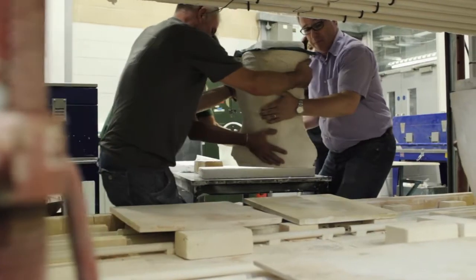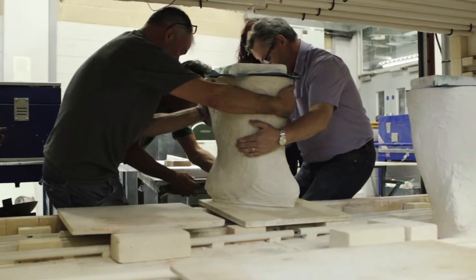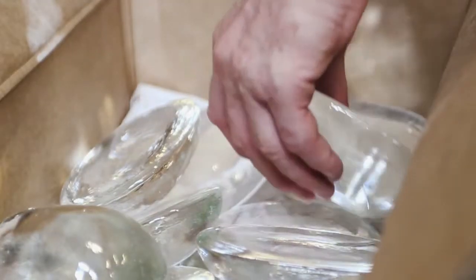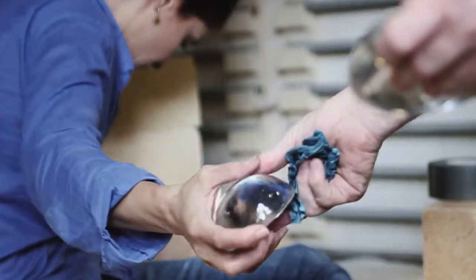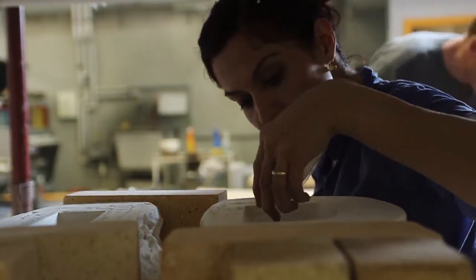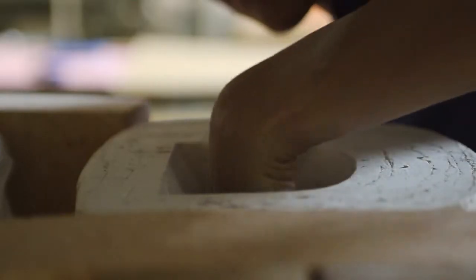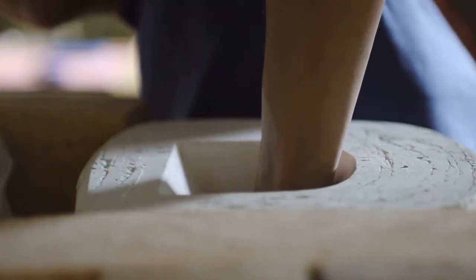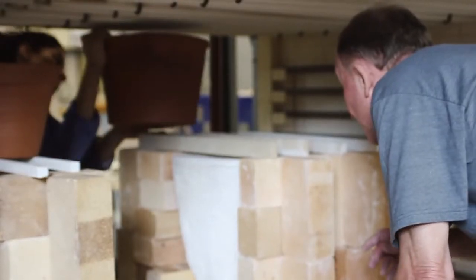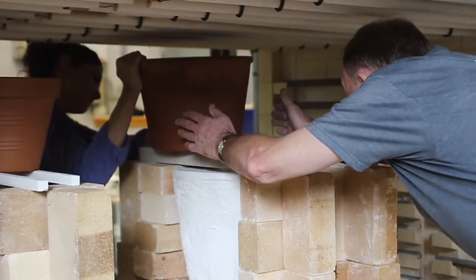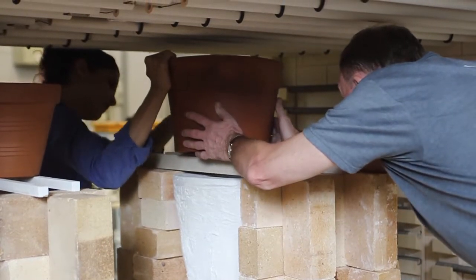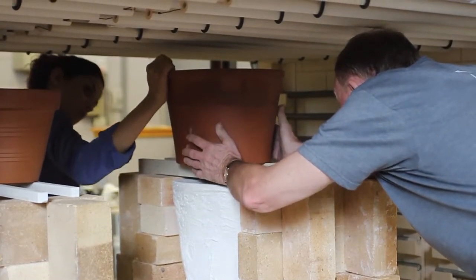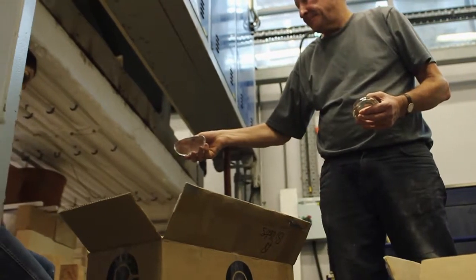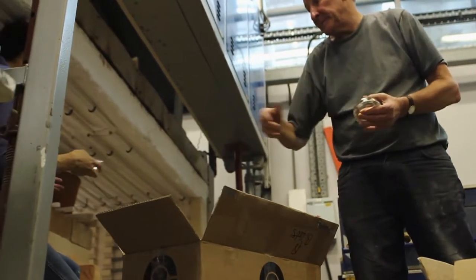The next stage is taking it to the kiln. Load the mold with glass. So I put about 20-25 kilos of glass into the mold, whatever I can get into the cavity of the mold, and then the rest of the glass, which is another 25 kilos, because the whole object weighs 50 kilos, I load into a flower pot. So I take a very, very big flower pot. I enlarge the hole that they normally have at the bottom, and put the rest of the glass into the flower pot, and all of this goes into the kiln.